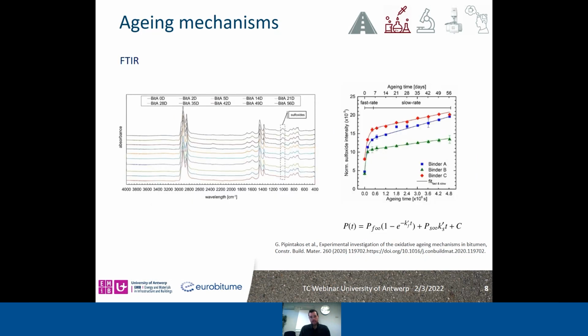The first technique, which is the most common one for research purposes and is used widely, is the Fourier transform infrared spectrometer, or FTIR. On the left, you can see spectra and how these evolved over time. And on the right, we have isolated the normalized sulfoxide intensity, which is considered one of the products of the fast rate phase. And we can see from this oxidation kinetics on the right that all the binders fit a model that takes into account the fast and the slow product. The fitting curve is based on this model, and the parameters were extracted from this model.